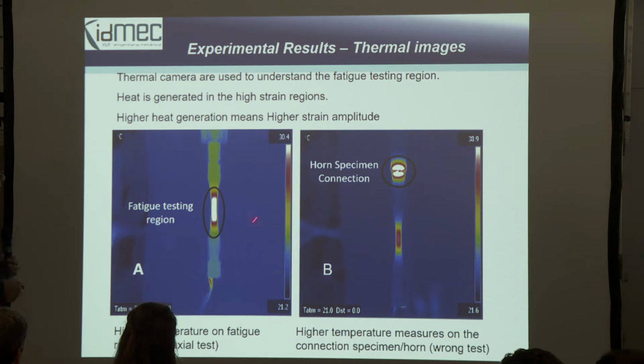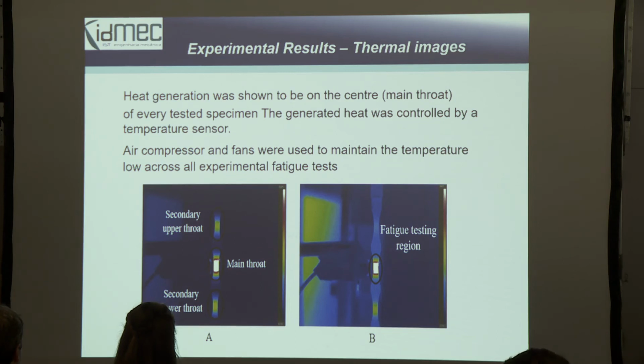Okay, before the results, in order to see if you have the correct behavior of the three-throat specimen, we must determine the temperature in each throat. This is a methodology that we already have for axial ones. This is for the axial one, there are no three throats. And this is the normal situation. This is a bad situation that was put there in order to see if our thermographic camera could detect higher temperatures. So for the three-throat specimen, here we have torsion here, we have torsion here, and some axial also, but the conjunction of maximum torsion and maximum axial is on the main throat, so this is the fatigue region. Because we always control our temperature on our machines, normally we don't go above 35 Celsius degrees.